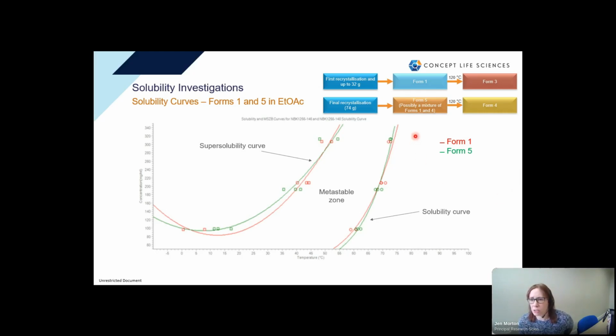So here we have the solubility curves generated from the clear points, as Carmen mentioned, form 1 in red and form 5 in green. And then we've got the supersolubility curves over here with the metastable zone in the middle. What you'll notice about these curves is that they're really very similar, almost on top of each other, which was perhaps slightly surprising, but we hadn't done this kind of work before, so we just took what we obtained.